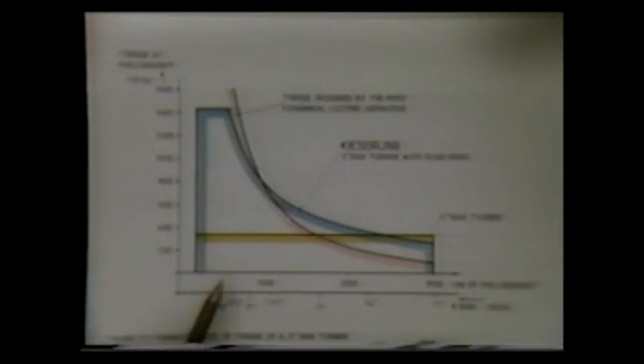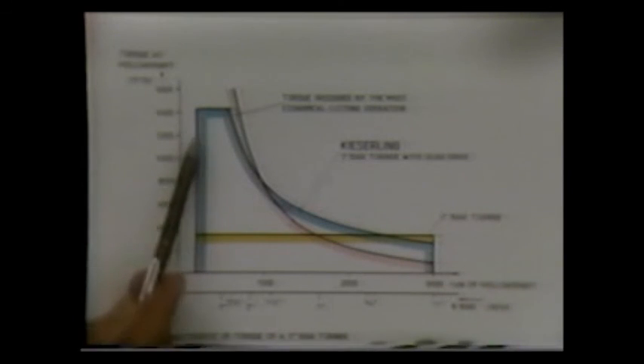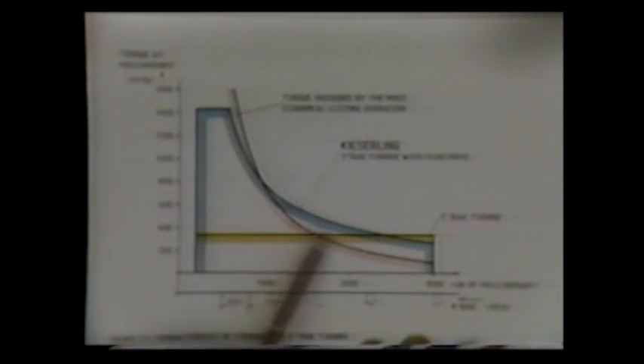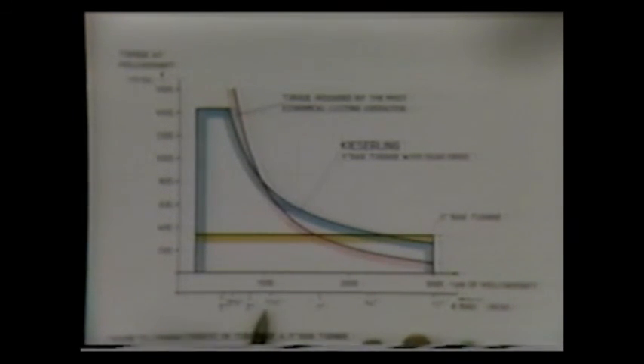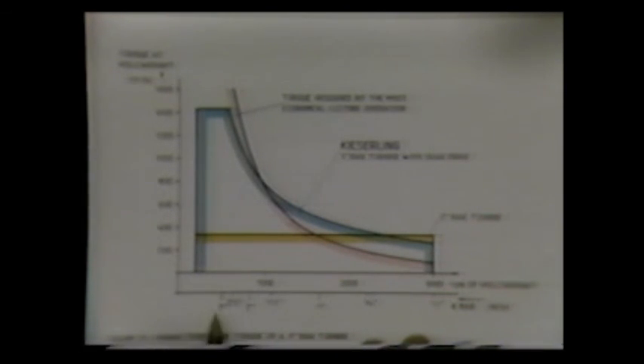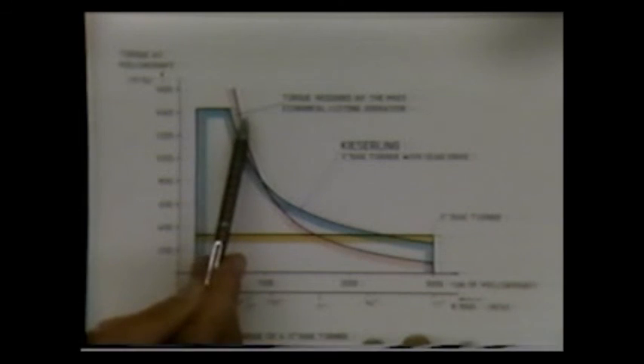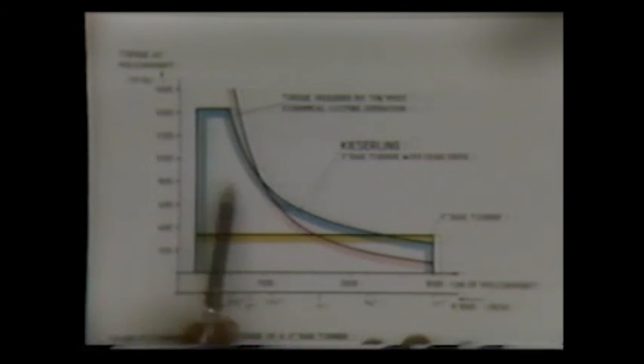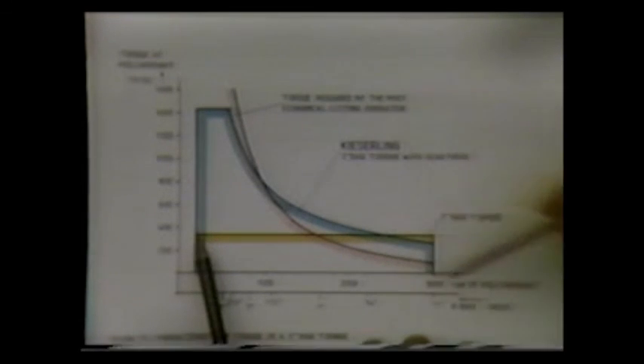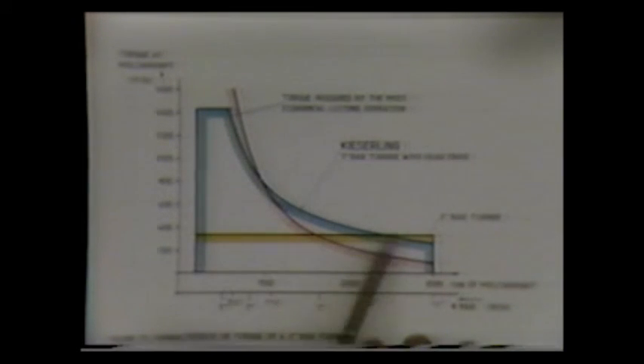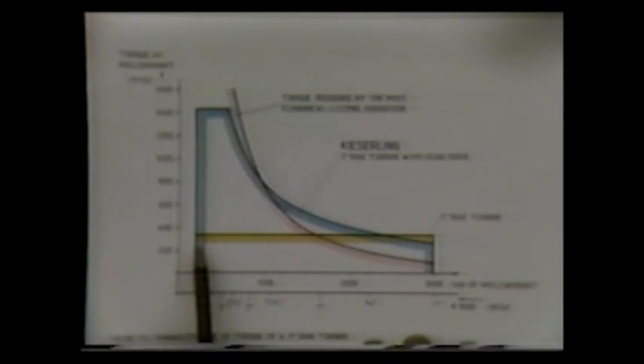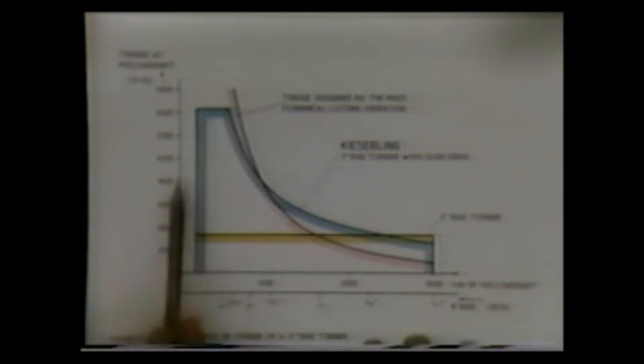You see here the blue one is a 3-inch bar turner from Kieserling, where, when you have to turn large diameters, 1.5 to 3-inch, you have a large torque available here. And when you have no field control, you have only this small torque available, and this is also a gap in production.